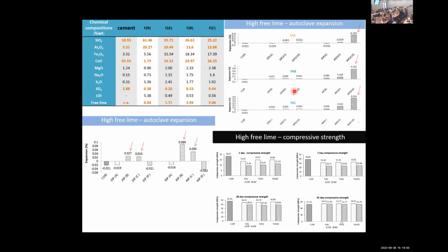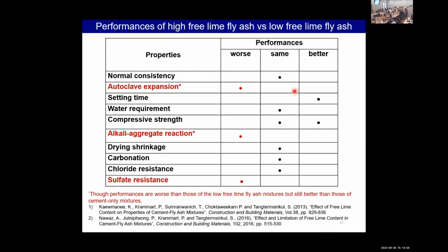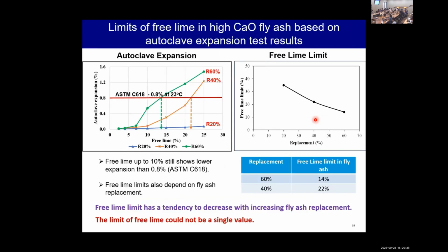We have studied the properties of concrete or mortar containing high free lime and compared with low free lime fly ash. We can see that the high free lime fly ash has worse expansion properties like autoclave expansion, alkali silica reaction, and sulfate resistance. But for autoclave and alkali silica reaction, the value is still better than OPC only. And of course, with high free lime content, setting time is faster, and compressive strength, especially at early age, is higher than low free lime fly ash.